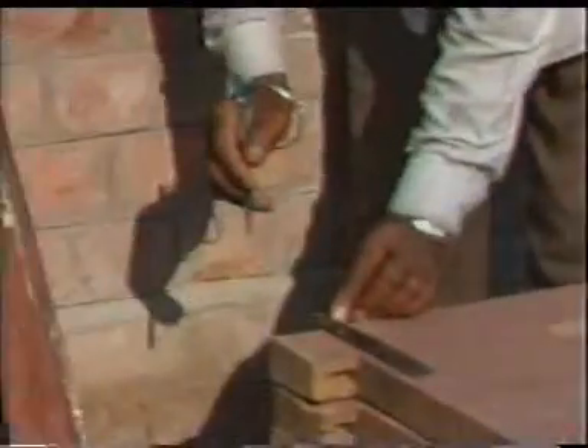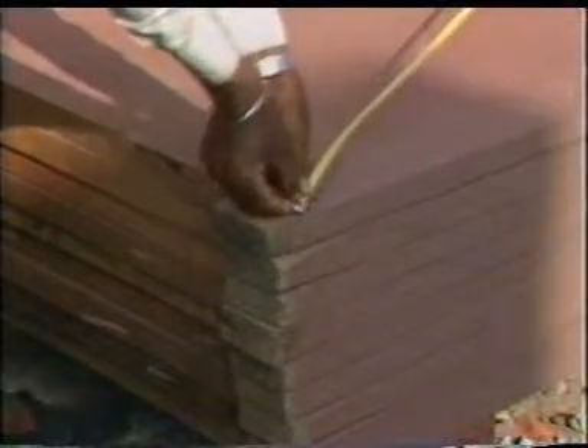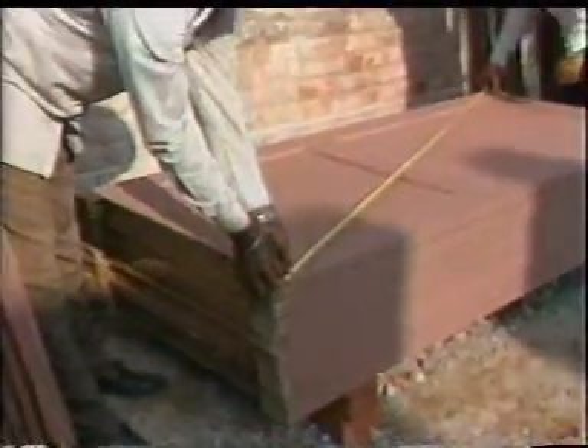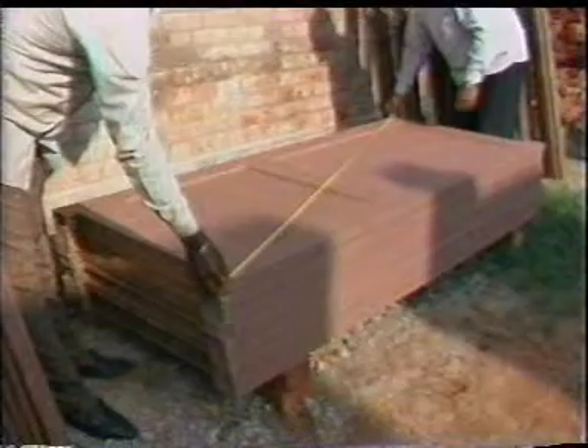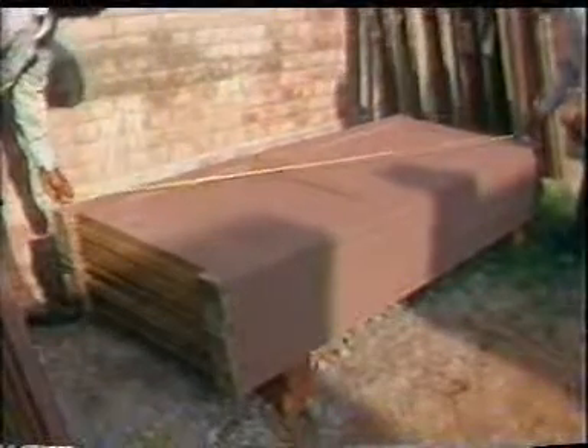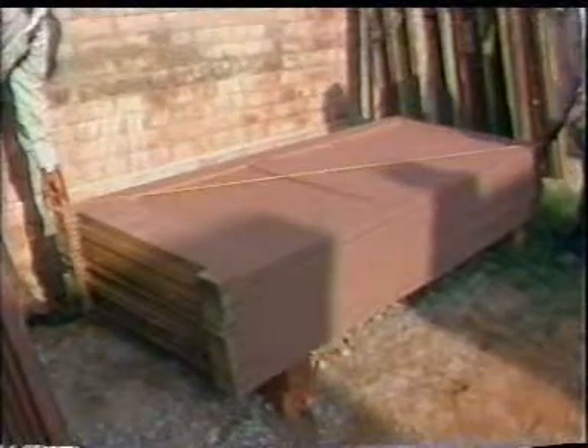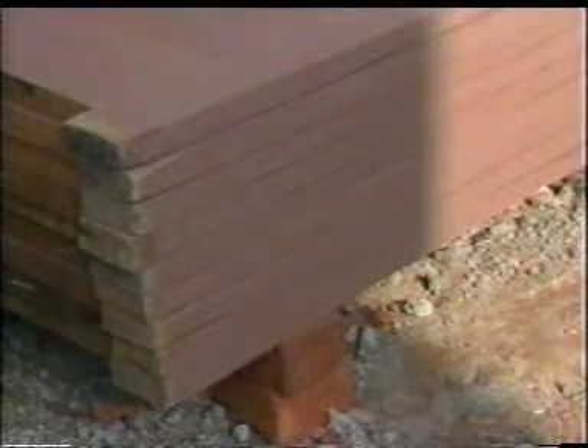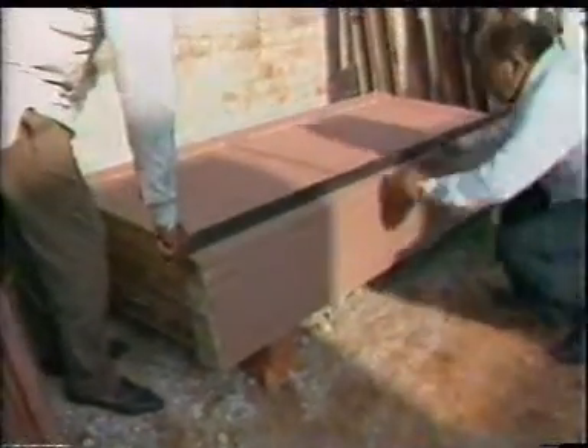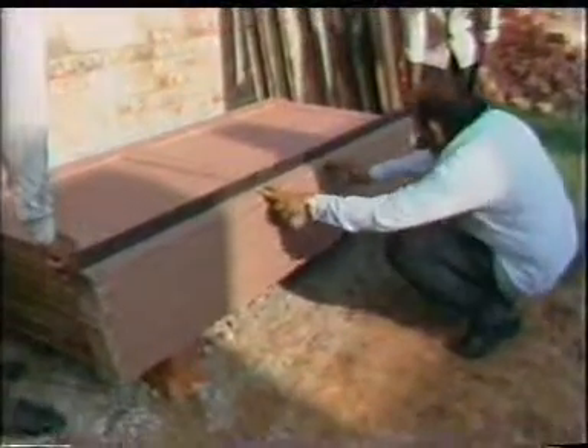Diagonal lengths are checked for squareness of the door. For this, mark the corner reference points with the help of a steel tri-square. Measure both the diagonals. There should be no difference between the two. To check that there is no warp or unevenness in the shutters, put a steel straight edge over its surface and check for gaps all along the straight edge.